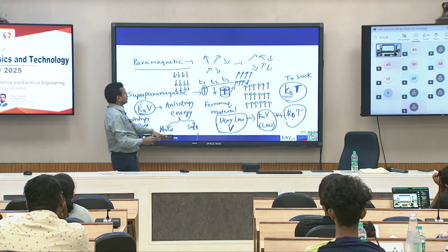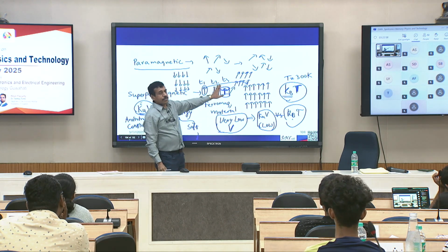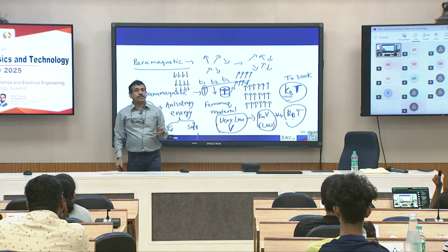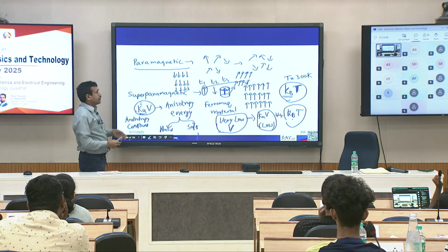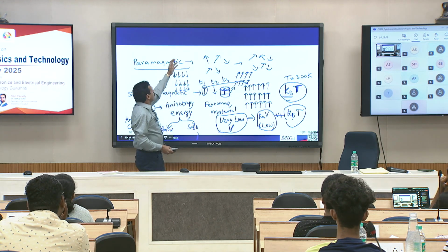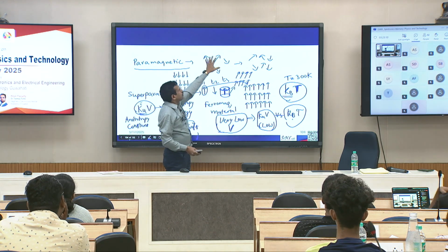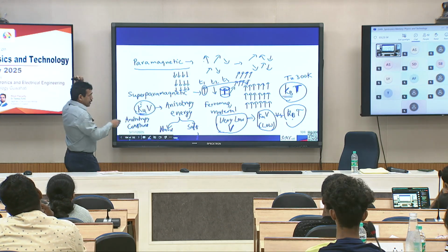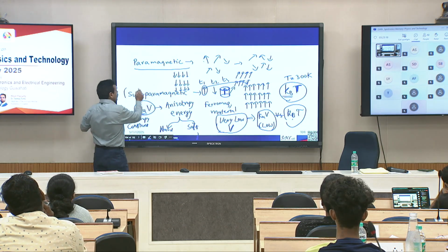So, your particle is still ferromagnetic, but the particle magnetization is fluctuating as a function of time, like the atomic magnetic moments fluctuate in a paramagnetic material. So, that phenomenon is called super paramagnetism.